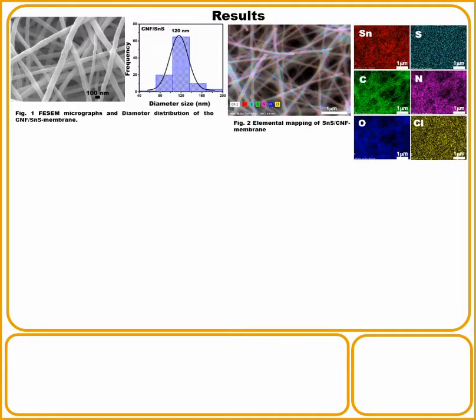Figure 2, the element mapping of the carbon nanofiber membrane with tin sulfide, shows the homogeneous distribution of tin, sulfur, nitrogen, oxygen, chlorine, and carbon among the carbon nanofibers. On the other hand, nitrogen, sulfur, and oxygen doping have been reported to be beneficial to sodium ion adsorption for the electrochemical reaction, and the presence of these elements in the composition would be advantageous for sodium ion storage.